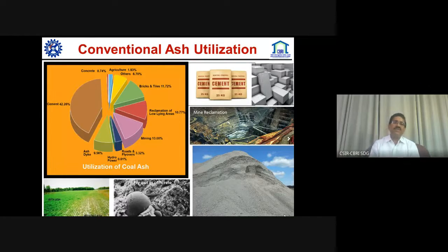Of the 60% utilized in different areas, the majority, about 40 to 43%, is used in cement. Cement industries mill it to a particle size finer than 4,000 square centimeters per gram, so that they can blend it into OPC, or mill it along with the OPC clinker. The next is bricks, where CBRI has played a very important role in developing PPC also, and we have produced bricks, blocks, tiles, etc.